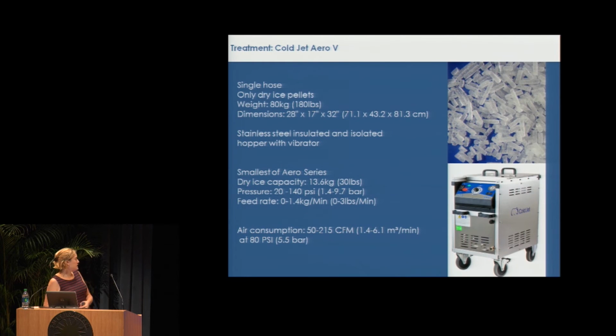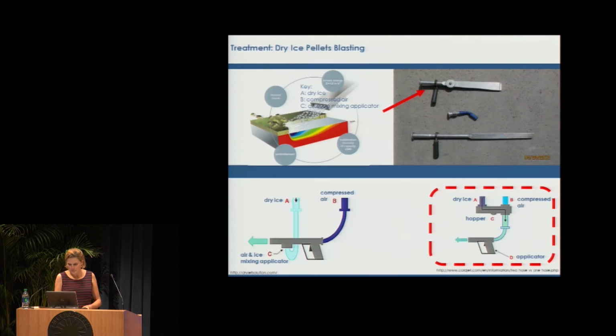So the machine itself has variable functions, which I really liked. The one is the feeding of the snow. So here you see that little button, you can feed the snow, so you can have fewer or more pellets that come out of the machine. And then, of course, there's a range between 20 and 140 psi of pressure. What was very important to us was also the variety in the nozzles, which was already mentioned. So you have the variety of the pressure, the variety of the feeding of the dry ice, and the variety of the nozzles. And these are the 3 nozzles that we, in the end, used most.